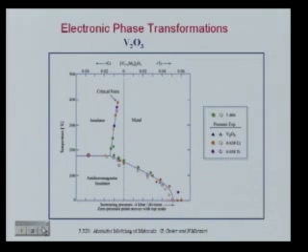This is its phase diagram in actually temperature pressure space, since there's no compositional axis. It's a stoichiometric compound. And at low temperature and low pressure, it's an antiferromagnetic insulator. If you actually raise the temperature, it becomes metallic and changes the structure. And it's completely driven by the fact that in the metal, the entropy of the electrons is higher than in the antiferromagnetic insulator.